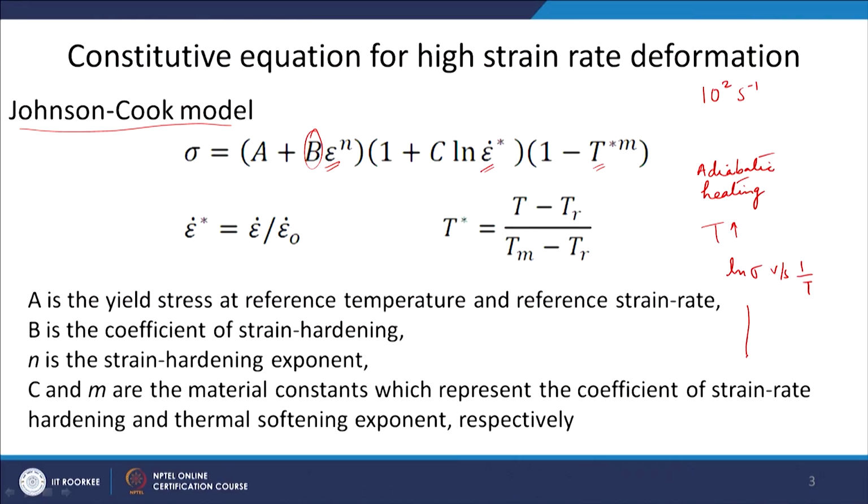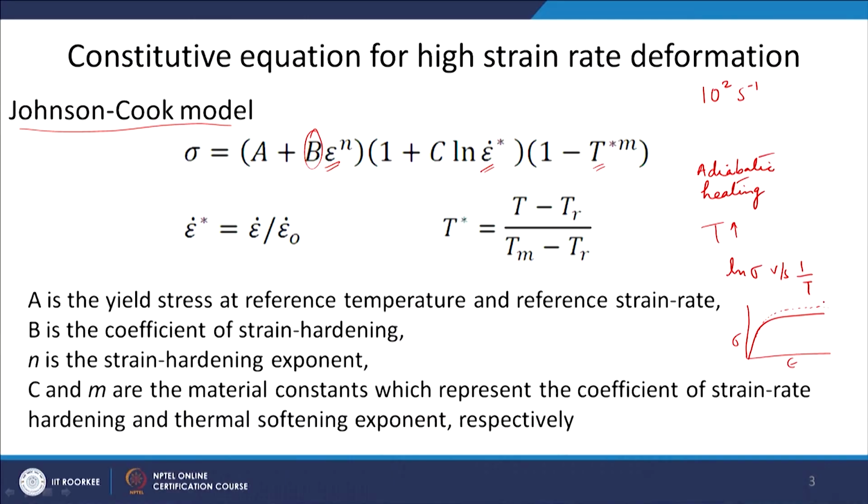That means if in a stress strain curve, this is my stress which I have measured, after the compensation the stress will obviously be higher than that, because the temperature should have been lower than that. Okay. So, this type of temperature compensation in stress you have to give when you are doing a high strain rate deformation.